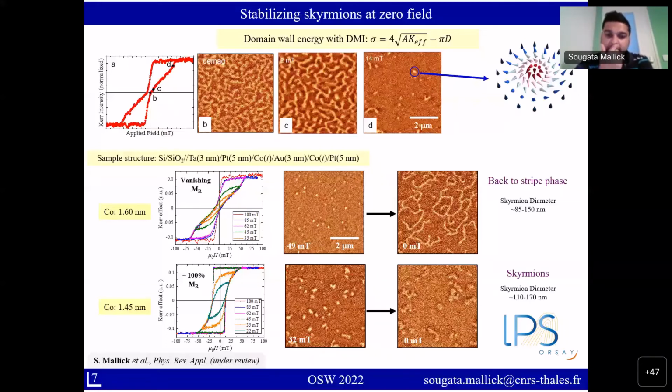However, the system I work on, the ferrimagnets, are very amorphous and I expect that they are very low pinned material, so I need to go to a tip thickness which is very low in magnetization. The tips which I have used for this study are 5 nanometer cobalt iron boron capped with 30 nanometer aluminum. So it depends on which system you are working on. We calibrate the tips every time before starting a new system.